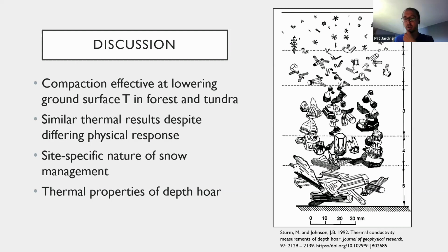The sites were dry, so there's less moisture available, which is bad for depth hoar, and the metamorphism appeared to be more spread out through the snowpack. At Dempster it's mostly in a thin layer at the bottom, whereas in Mayo, it seemed like it was almost all the way through to a lesser extent. So the Dempster sites were unknowingly set up over a drainage ditch, so there's tons of moisture available. I'm not familiar enough with depth hoar development to know if this is a thing, but because the wind slab snow above it was mostly impermeable, it seems to me like the water vapor was getting trapped at the bottom of the depth hoar, and that might have caused it to metamorphize into a much higher stage more quickly, because it did look much more crumbly compared to Mayo.